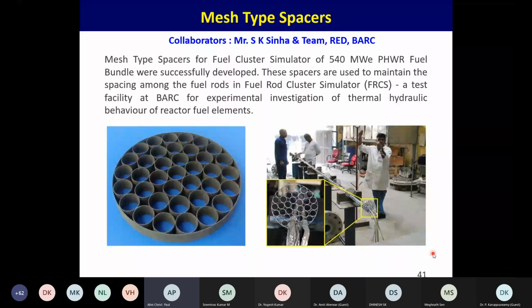Another pretty beautiful example is making these mesh type spacers. You see, it has got 37 holes. The wall thickness is 0.4 millimeters, and you see you have diamond shapes, triangular shapes, and circle shapes. The conventional way of making this was, they used to take a block and do EDM wire cut, because when we talk of a wall thickness of 0.4 millimeter, the deviation they want is 50 micron. So wire cut was the solution.